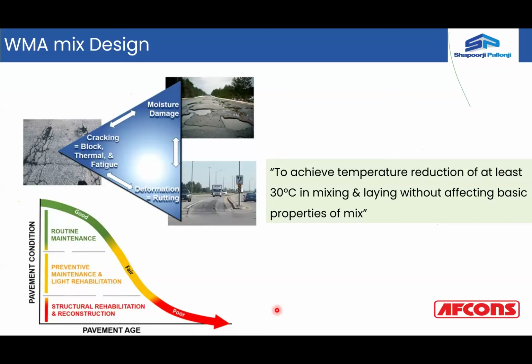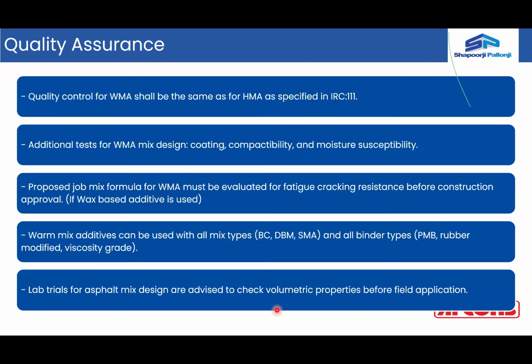But the rutting cannot be addressed if you are not able to reduce the temperature of the mix, because if you're not reducing the temperature of the mix and allowing the rolling operations at a higher temperature of 160 to 170 degrees, then you will have an envelope during the initial rolling stage only, because of the presence of the tires, and then you will get the rutting at a later stage. So these are a few things which you need to take care of during the operation of construction. And when you talk of quality assurance and quality control, the WMA shall be the same as HMA as specified in IRC:111. But for the additional tests, the warm mix design, the coating ability, the compactability, and the moisture susceptibility need to be checked.